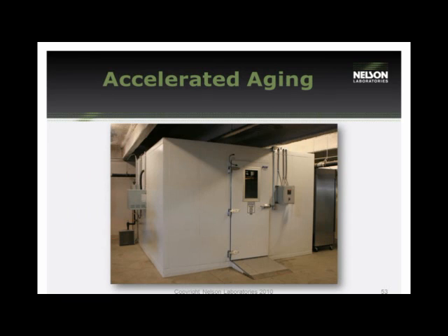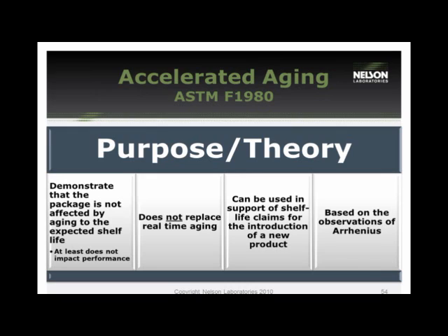Okay, we're going to move into stability testing now, and this is regulated using accelerated aging. Accelerated aging is regulated under the standard F1980. The purpose behind it is to demonstrate that the package hasn't been affected by its shelf life. It does not replace real-time aging. Real-time aging is required to be performed in conjunction with accelerated aging, and they should start at exactly the same time point. Determining the length of your accelerated aging is actually based on an equation and observations by Arrhenius.